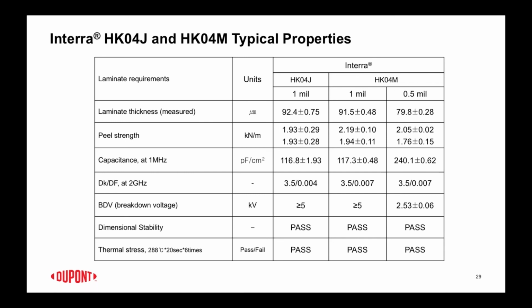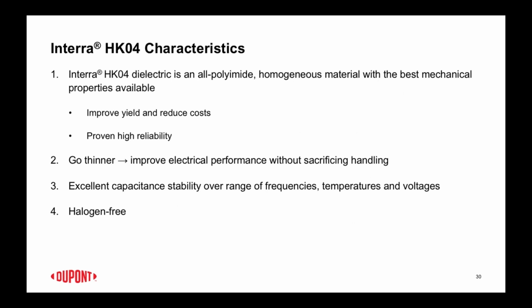They have excellent dimensional stability, and they handle the thermal stress, 288 C, 20 seconds, 6 times solder floats with no problem. Again, polyimide is a very high temperature polymer system. In fact, it's usually the highest rated material inside the circuit board. It's better than the material that's surrounding it, making up the rest of the circuit board. Like I mentioned, it's a homogeneous system. It's all polyimide. Because of that, it has very good yields, and it reduces your overall cost to make these layers. And it has very proven high reliability.